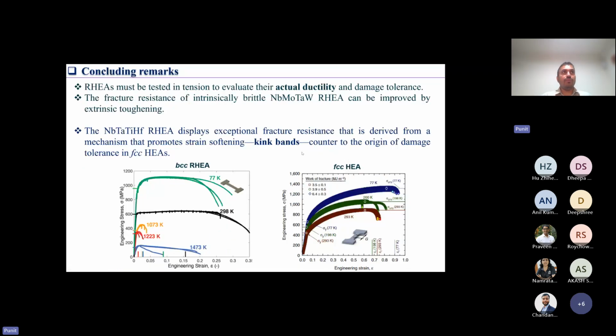So coming to the conclusion of my talk, the first part, where I talked about niobium, molybdenum, tantalum, tungsten, shows that for refractory high entropy alloys, before we claim that they are the structural materials for the future, we need to evaluate their actual ductility and test them in tension. And in some cases, if your material is really brittle, like niobium, molybdenum, tantalum, tungsten, intrinsically brittle, you can improve the fracture toughness by extrinsic toughening.